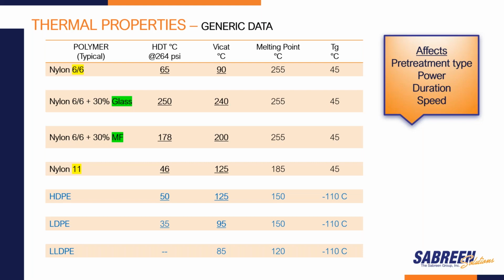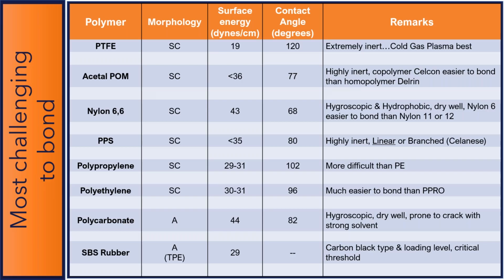Another example of this is nylon 11, which is very commonly specified. Nylon 11 just happens to be more difficult to bond than nylon 6/6, or nylon 66 plus 30% glass, and that's due to the longer molecular chains. So if we want to improve our bonding just by changing the material, then we can do that by changing from nylon 11 to nylon 66. But again, we always have to be very cognizant of the polymer properties. And a similar type effect for polyethylenes, whether it's high-density polyethylene, low-density polyethylene, or linear low-density polyethylene, thermal properties matter.